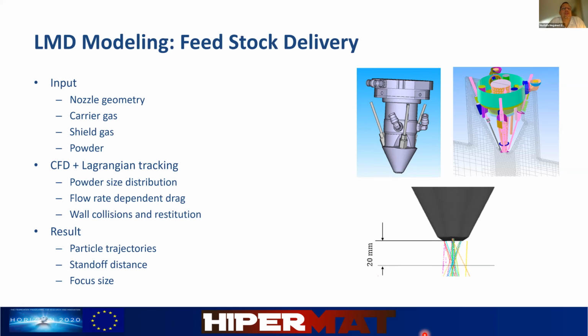We account for the drag between the gas flows and the different particles. Here we take into account things like turbulent drag, particle sizes, and the concentration of the particles. And we also take collisions of the particles with different walls. This collision will extract energy from the particles, and the remaining energy will be the remaining kinetic energy for the particle to continue its trajectory as it moves out of the nozzle.